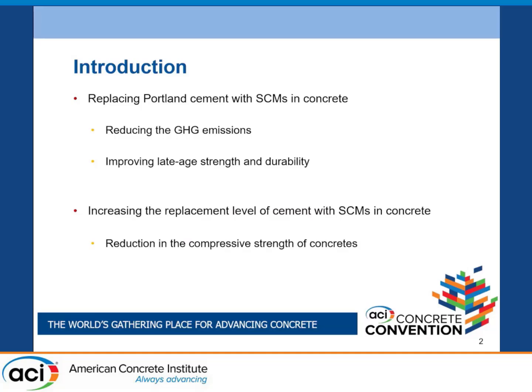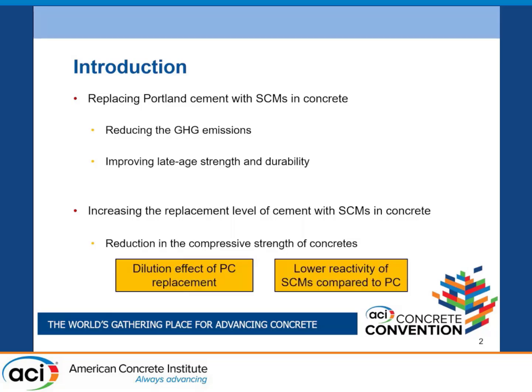But when we increase the replacement level of Portland cement with SCMs beyond the currently used levels, we will see a reduction in compressive strength, which is very significant at early ages. This is because of the dilution effect of Portland cement replacement, since we have less PC in our concrete which is reacting, and also because of the lower reactivity of SCMs compared to Portland cement.